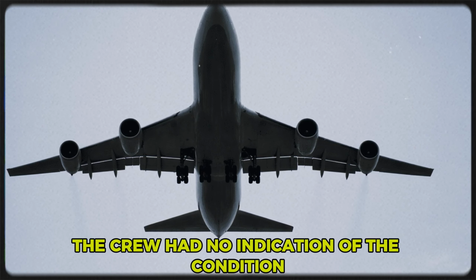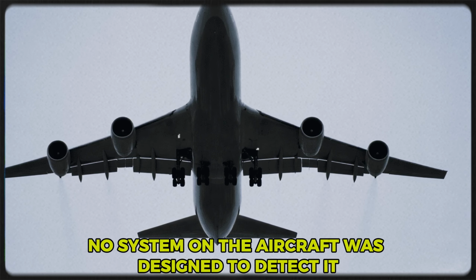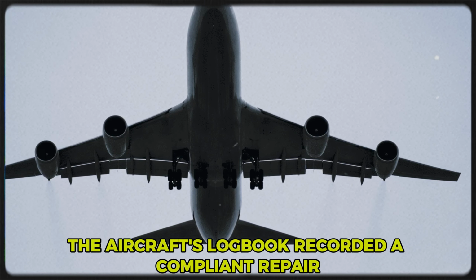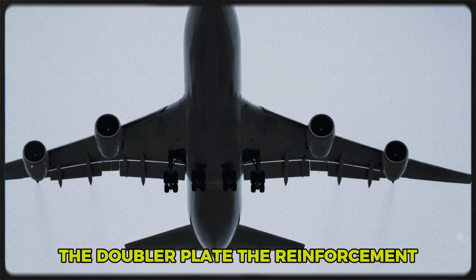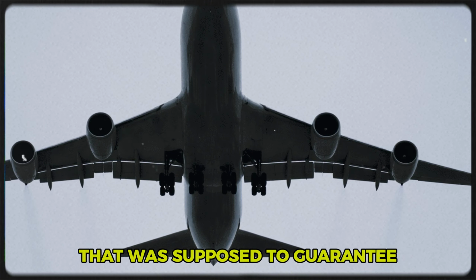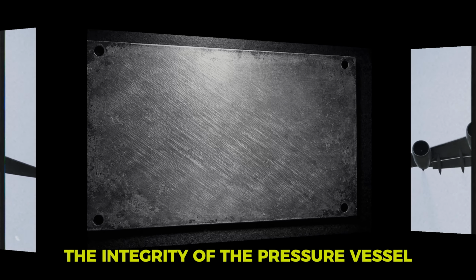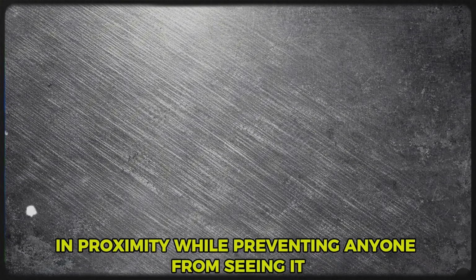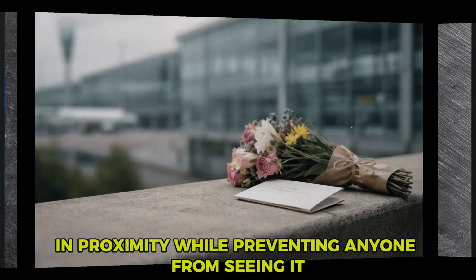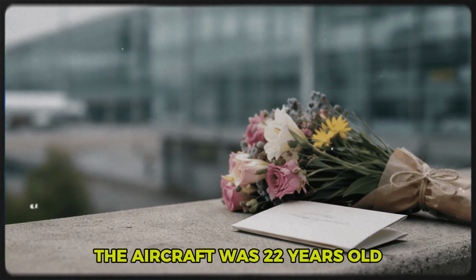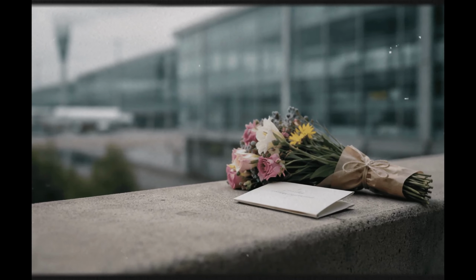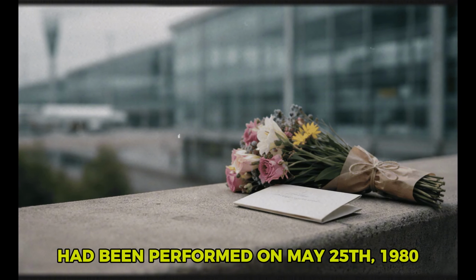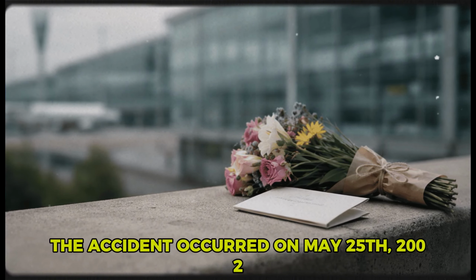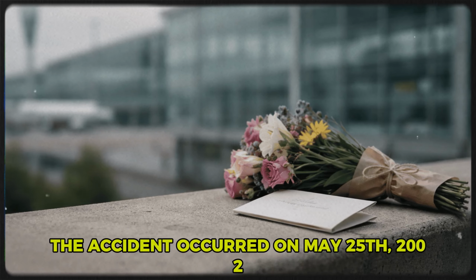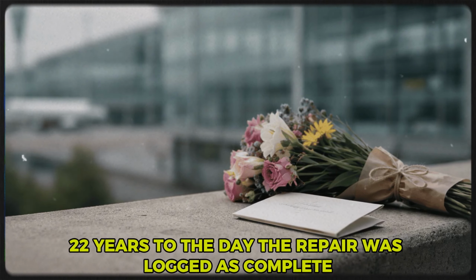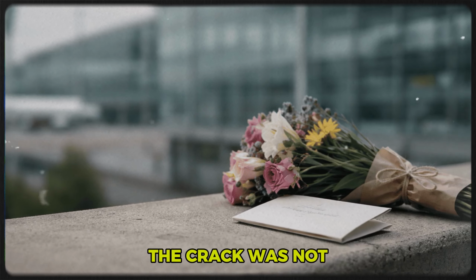The crew had no indication of the condition. No system on the aircraft was designed to detect it. The aircraft's logbook recorded a compliant repair. The doubler plate, the reinforcement that was supposed to guarantee the integrity of the pressure vessel, was holding the two sides of a 6-foot crack in proximity while preventing anyone from seeing it. The aircraft was 22 years old. It was on one of its last flights. The repair that would destroy it had been performed on May 25, 1980. The accident occurred on May 25, 2002, 22 years to the day. The repair was logged as complete. The crack was not.